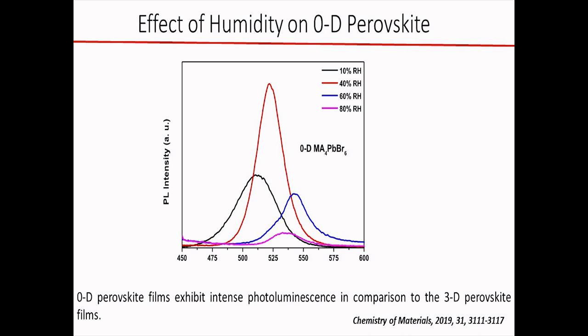The 0-dimensional perovskite, shown here in red, has shown a huge photoluminescence. Whereas if we increase the humidity, the luminescence has reduced, because probably the methyl ammonium ions present are helping with the recombination process, and that's the reason why the photoluminescence is reduced.